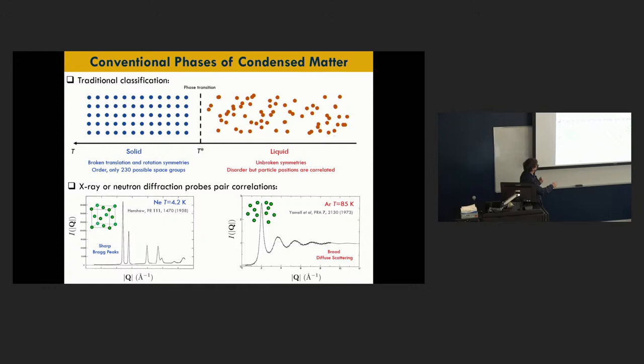So imagine we just warm up this, and we go to the liquid phase, and we see that the diffraction pattern of this liquid keeps some of the characteristics of the solid. In particular, there are peaks, but these peaks are broad and diffuse. So liquids keep some organization that informs on the way they're going to crystallize, and these oscillations here in the structure factor are a signature of the correlations between the atoms.